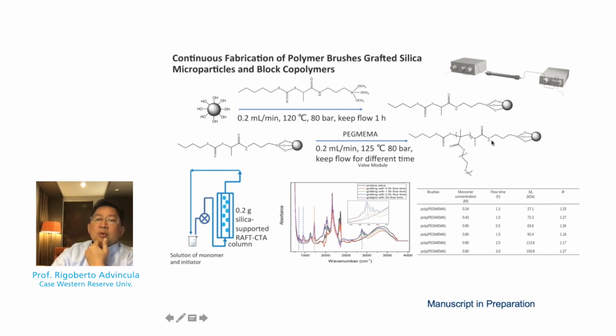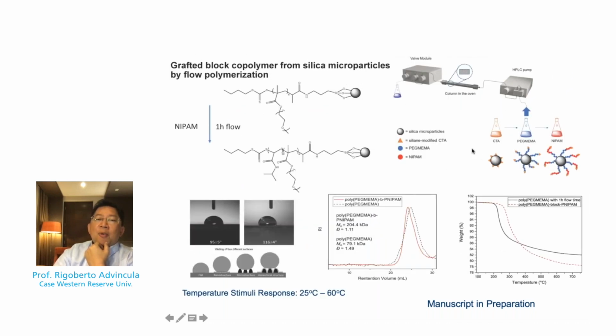For example, to coat the silica particles with a hydrogel based on PEG methacrylate, both homopolymer and block copolymer strategies. So here we coated the particle with polyethylene glycol methacrylate followed by poly NIPAM, or N-isopropyl acrylamide, which resulted in a hydrogel coating itself.